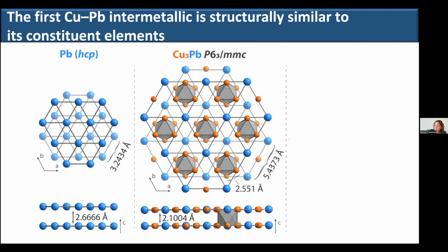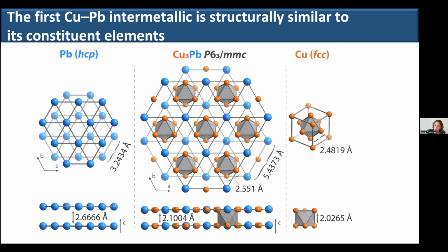We synthesize this at about 16 GPa. That structure becomes the stable structure around 13 GPa. We've found we cannot access this structure below that pressure. And if you look at copper, which maintains the same structure across the entire pressure range, you can almost envision this as an expanded lattice of the HCP lead phase interwoven with the copper units.